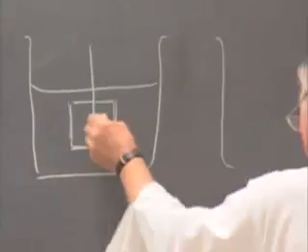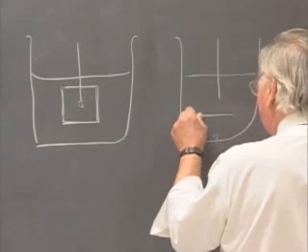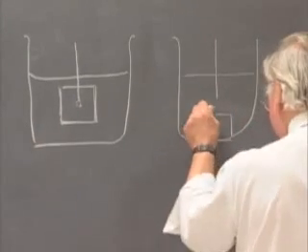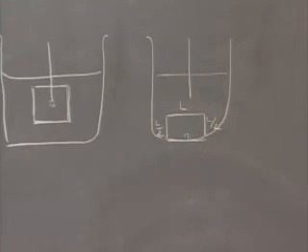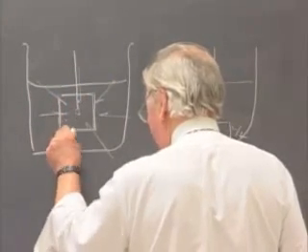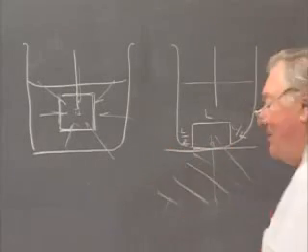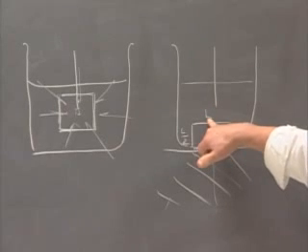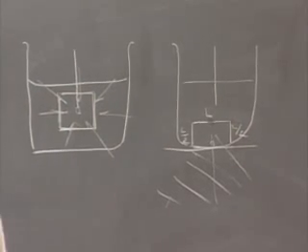Now, unless you attach this little seed crystal carefully, there would be a good chance that it would fall off and land on the bottom of the beaker. When that happened, your crystal would not have the shape of a cube. It would have a shape in which these two top edges had length L, and these faces on the side were exactly half that length. And what's happening is that this crystal is growing in an unconstrained environment. The nutrient is coming out and crystallizing from all directions. In this case, nutrient can't get in from the directions that are below the crystal, so the growth in that direction is eliminated, and this height is exactly half that of the edge of the crystal. So that's sort of a very specialized case of a crystal growing in a constrained environment.